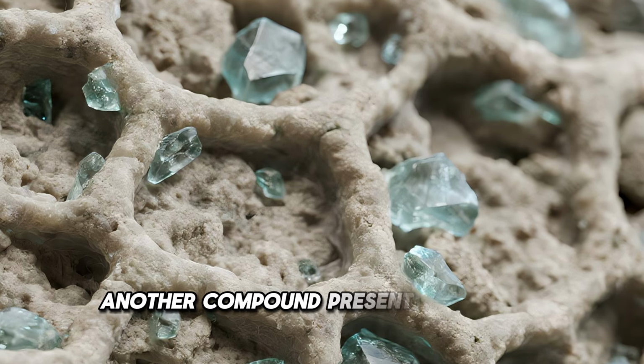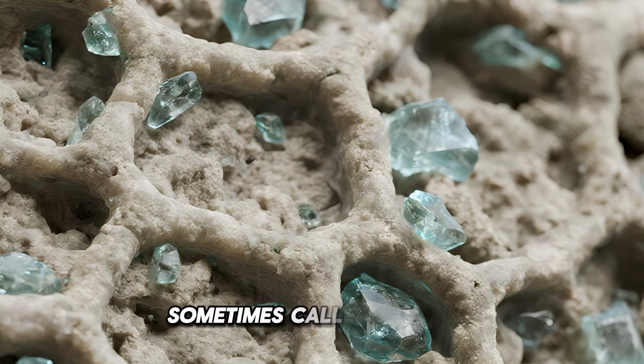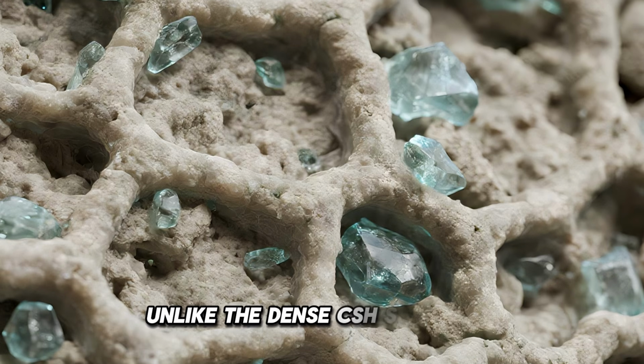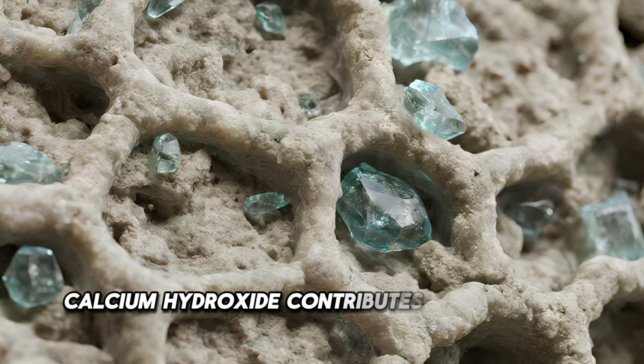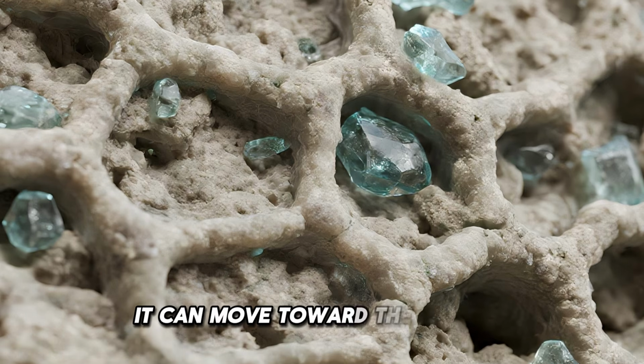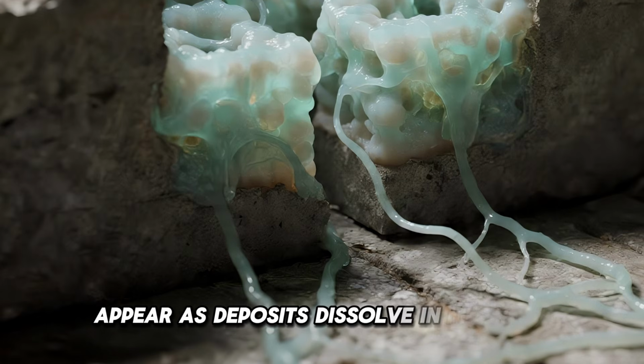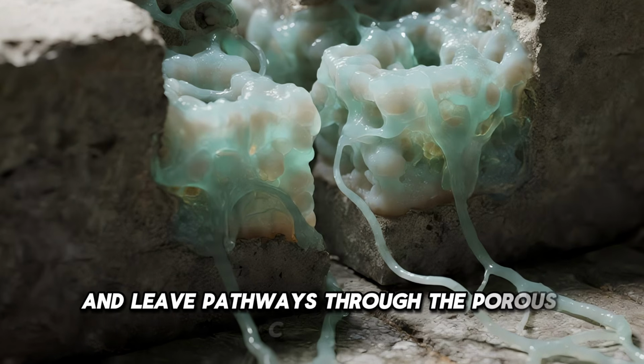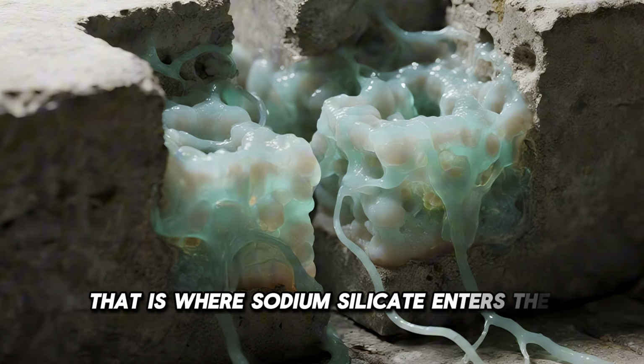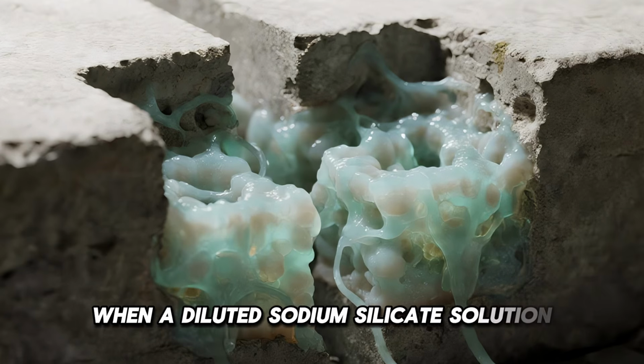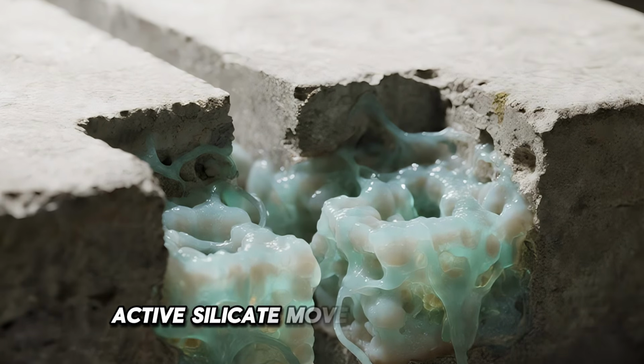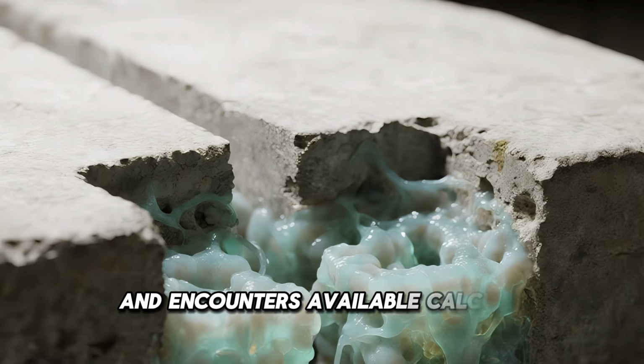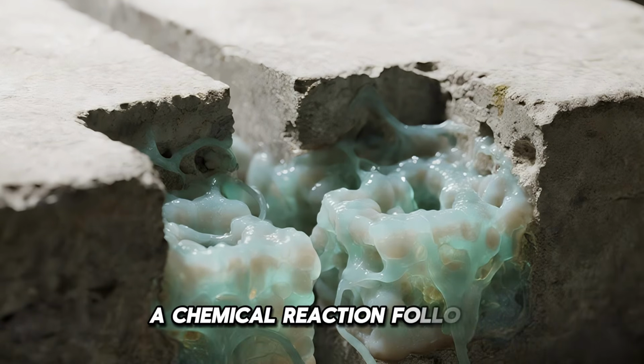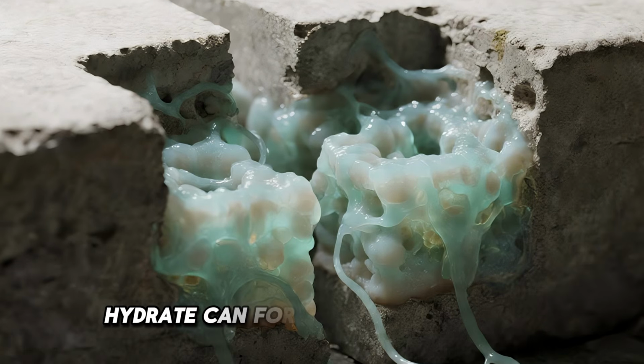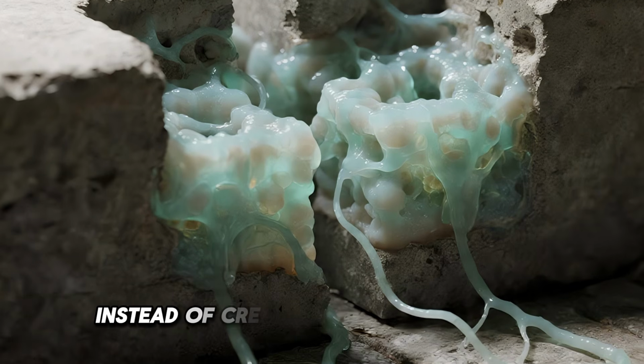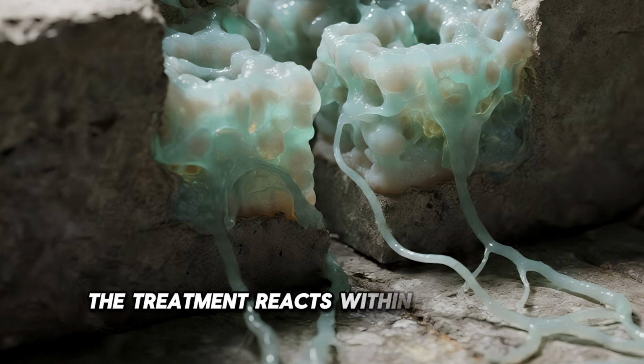Another compound present is calcium hydroxide, sometimes called free lime. Unlike the dense CSH structure, calcium hydroxide contributes much less to strength. It can move toward the surface, appear as deposits, dissolve in moisture, and leave pathways through the porous concrete. That is where sodium silicate enters the picture. When a diluted sodium silicate solution penetrates concrete, active silicate moves into the pores and encounters available calcium compounds. A chemical reaction follows. New calcium silicate hydrate can form inside those spaces. Instead of creating only a film on top, the treatment reacts within the mineral structure.